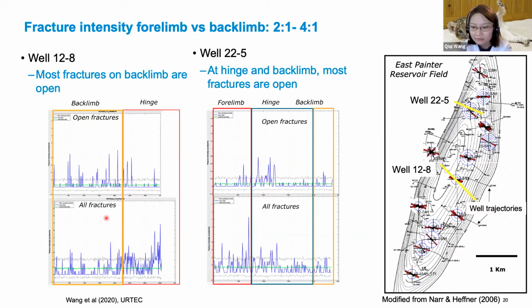We see, so the hinge section of the wells shows higher overall fracture intensity, but fewer open fractures. It tells us a large proportion of the fractures in the hinge interval of the wells are sealed. On the other hand, most fractures in the backlimb are open. And similar in this well on the right side, which was drilled into the backlimb and penetrates through the hinge and the forelimb. In this well, we see most of the forelimb fractures are sealed. In contrast, those at the hinge zone and the backlimb are open.